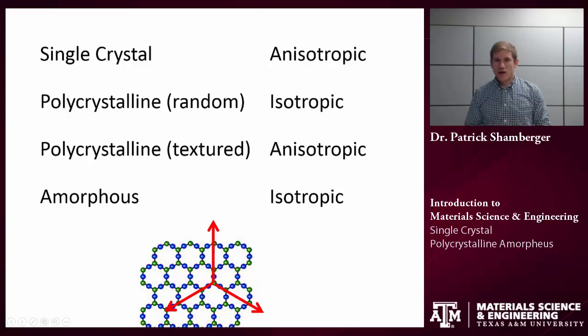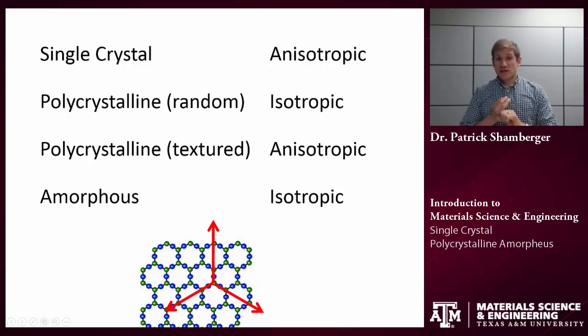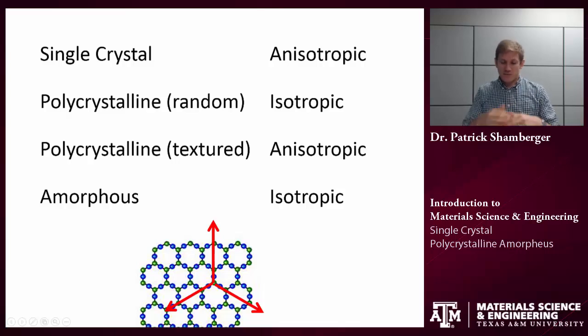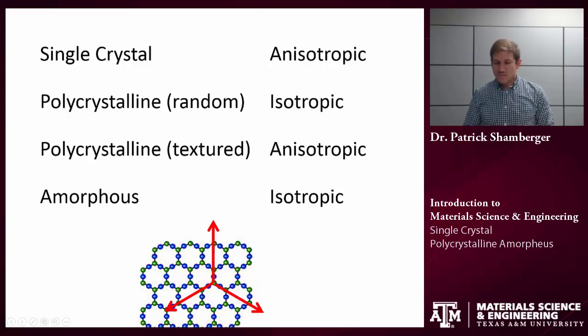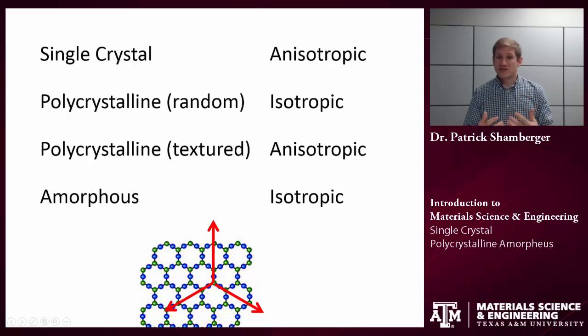In summary: single crystals are always going to be anisotropic. Polycrystalline materials that are randomly oriented are isotropic, but once we manipulate them by rolling or drawing, we texture them — give them a preferred orientation — and that makes them anisotropic. Amorphous materials with no long-range order are always isotropic. The other important lesson is that the symmetry of the properties of a material depends on the symmetry of the single crystal itself.